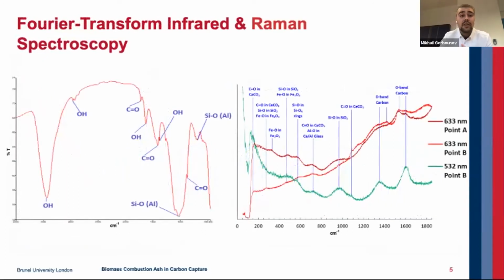Apart from that, we have also done the Fourier transform infrared spectroscopy and the Raman spectroscopy. But the key thing to bear in mind about these techniques is that they are perhaps better suited for identifying organic matter rather than inorganic material and mineral phases. And the reason being that covalent bonds are more prominently displayed on the spectra than ionic bonds. The reason for this phenomenon is the fact that strong ionic bonds do not vibrate strongly after infrared absorbance, i.e. do not change the dipole moment during internal vibrations, and therefore they're less detectable.